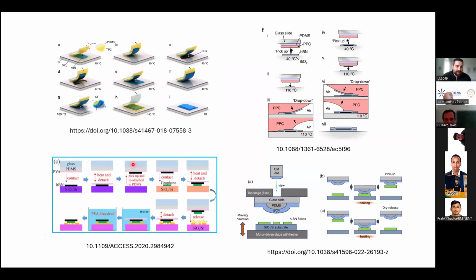Another way to avoid high temperatures is using PVA instead of PC and dissolving it in water. But again, water can introduce moisture to the system that you don't want. I personally prefer this dry technique, and a similar one is what I use in the lab, where we use PPC. This does not need to be dissolved in chloroform. You just need to use temperatures within the glass transition range, which is between 40 and 60 degrees for PPC. In this range, this polymer will behave partially like a liquid and partially like a gel, like I would say a solid film, but it has high flexibility and high control.